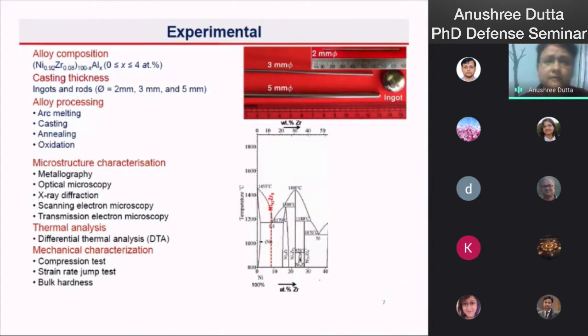The experimental part of my work: I prepared the ingots and rods of diameter 2 mm, 3 mm, and 5 mm by arc melting and in situ suction casting technology. After that, some of the samples I annealed and some of the samples I oxidized, to check their annealing properties and oxidation behavior.